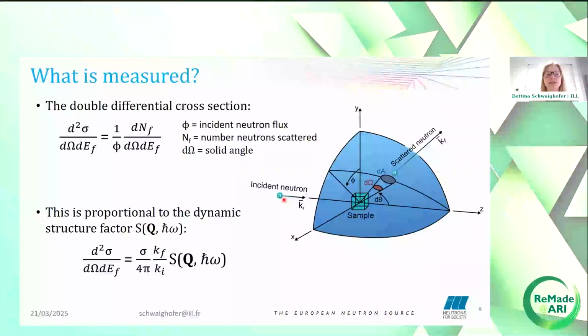The quantity we actually measure in a neutron scattering experiment is the number of neutrons scattered per second into the solid angle d theta with a final energy Ef between Ef and Ef plus dEf. This is called the double differential cross-section. The double differential cross-section is proportional to the dynamic structure factor S(Q, omega). S(Q, omega) depends on the momentum transfer Q and the energy transfer omega, and it therefore contains all experimental information.